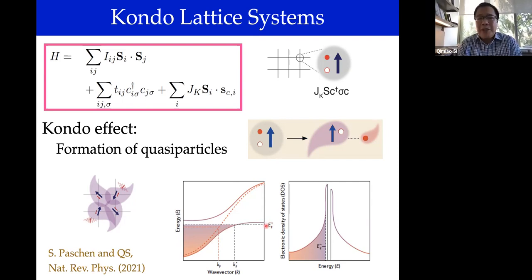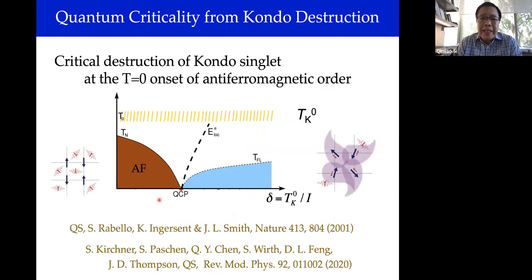So if we want to destroy the quasi-particles, one way to proceed is to mess up the Kondo effect. And that's in fact the picture that was advanced, namely if we tune the control parameter, which could be thought of as this Kondo scale divided by the RKKY scale. When the Kondo scale dominates, we end up with the Kondo singlet ground state as depicted here, and that leads to the development of quasi-particles. And there's a scale which will characterize it, a low energy scale that will be non-zero. This is a scale which happens below the single-ion bare high energy Kondo scale, the onset of Kondo correlations. There's a development of fully developed Kondo singlet and quasi-particles.